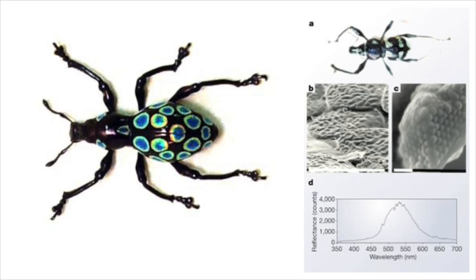However, Pachyrhynchus argus exhibits a uniform metallic coloration that remains visible from all viewing angles. This omnidirectional coloration arises from a photonic crystal structure analogous to that found in opal. The color is produced by scales approximately 0.1 millimeters in diameter that occur in patches on the top and sides of the beetle's roughly hemispherical body. These flat scales lie parallel to the body surface and consist of two components, an outer shell and an inner structure. In some scales, the inner structure is absent, rendering the entire scale transparent.